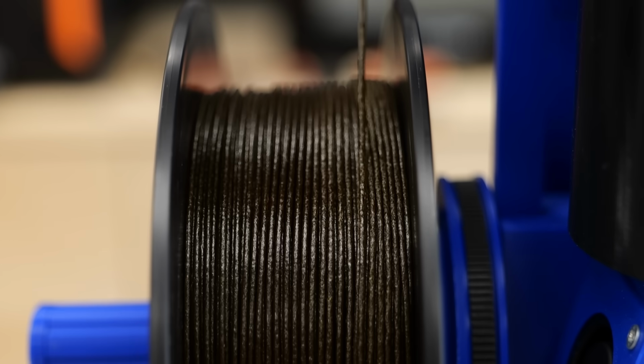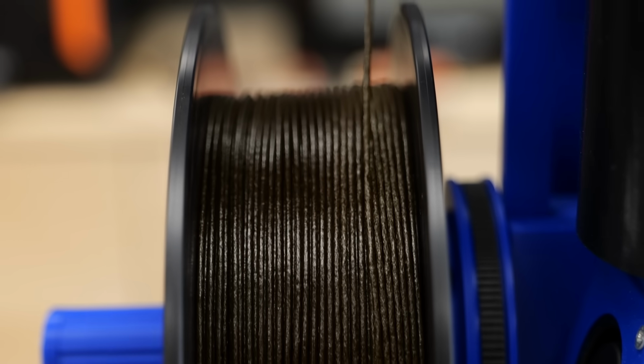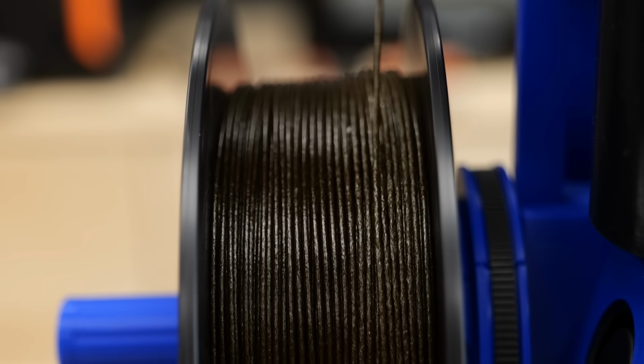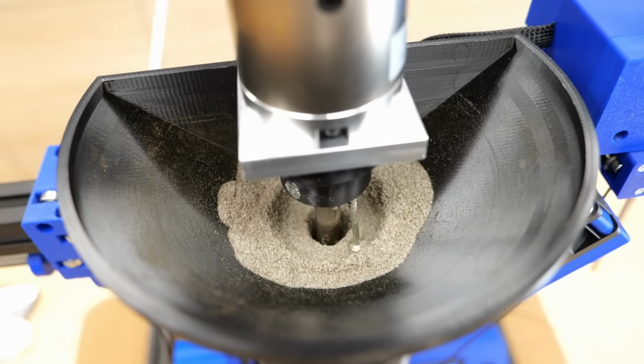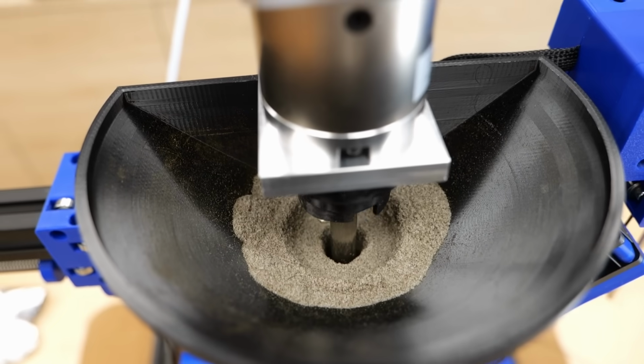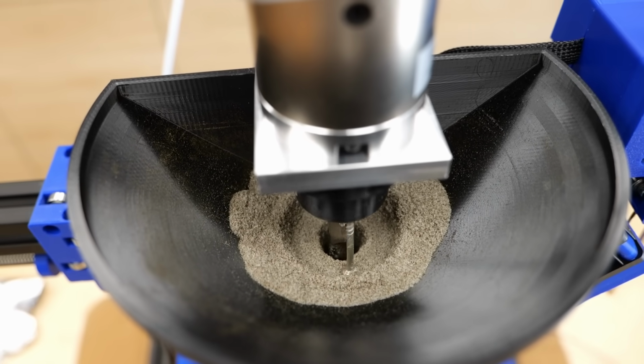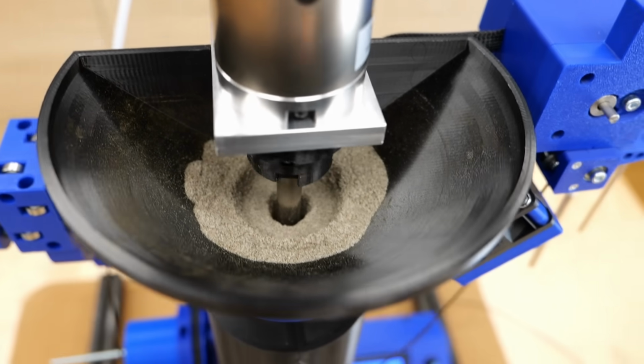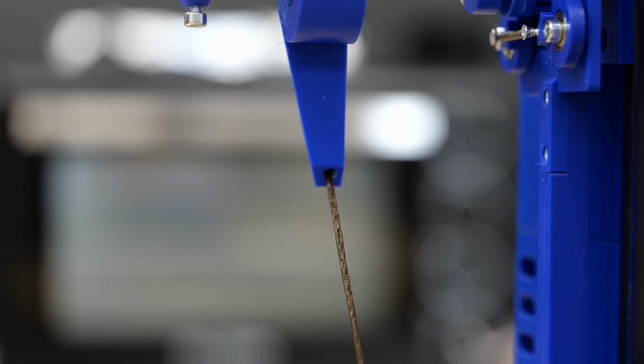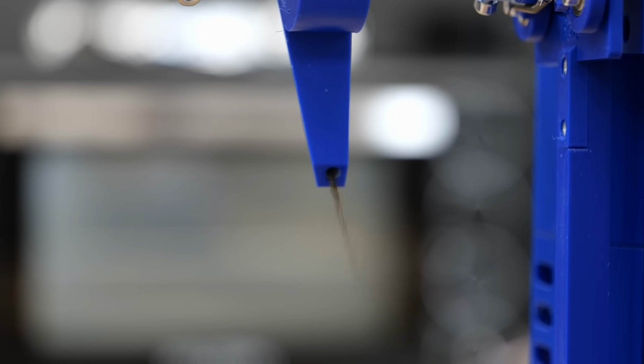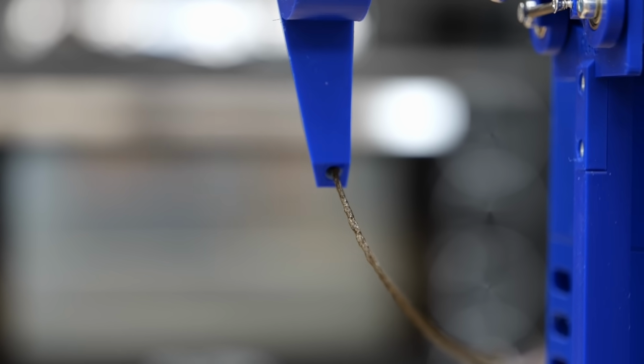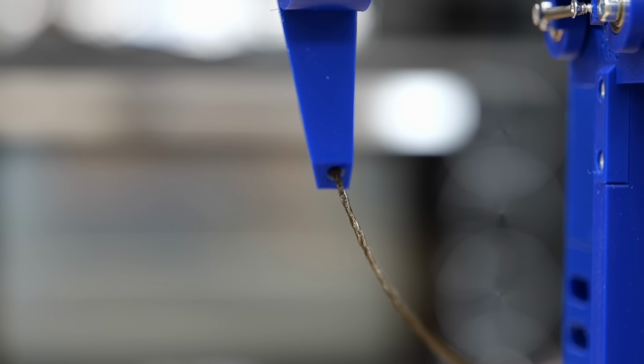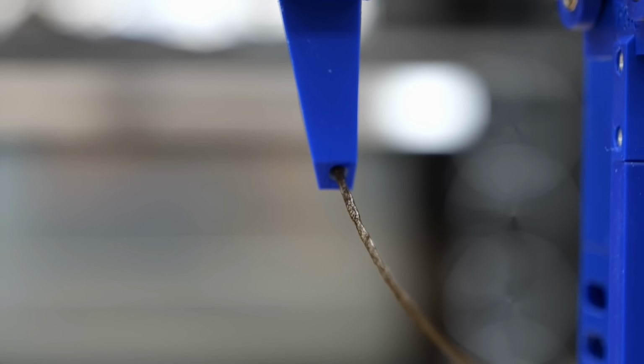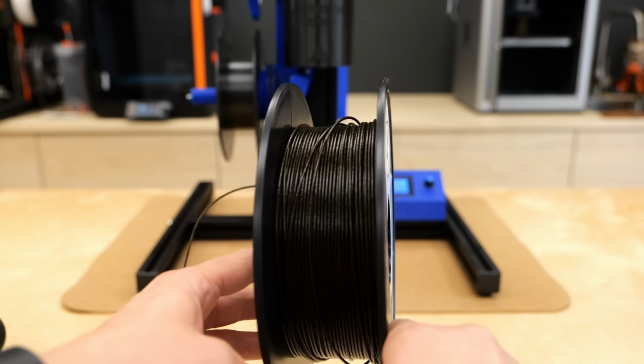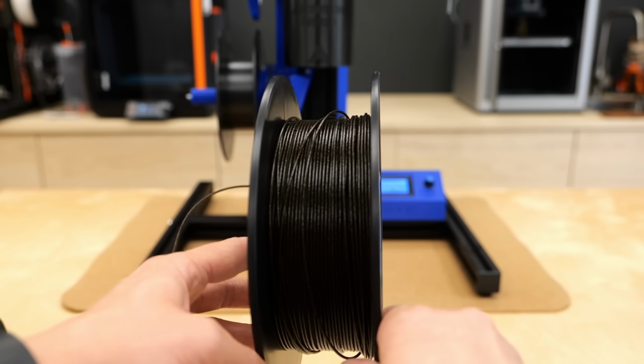It could have been moisture, but since the material was only out for half an hour, it doesn't seem super likely. I rather think that I had a feeding problem, because the fine PLA particles don't flow as well as the pellets did, which resulted in inconsistent material flow and therefore also inconsistent pressure within the extruder. If you have more experience than I do, please let me know, because this wasn't the only time I had this problem here. I still ended up with a nice sample of cow dung PLA that looked much better than my previous batches.